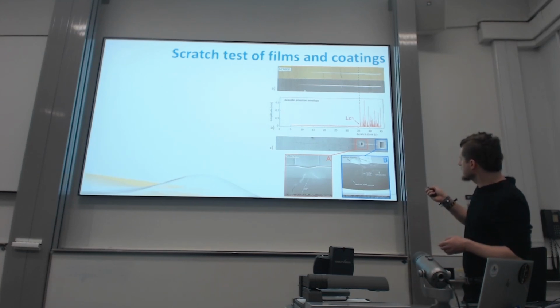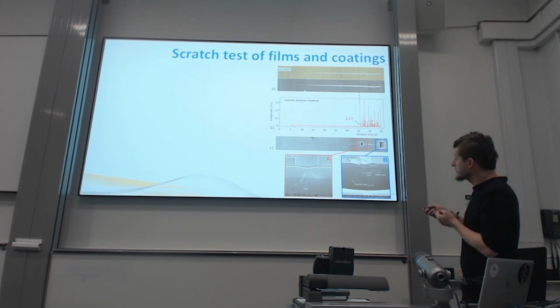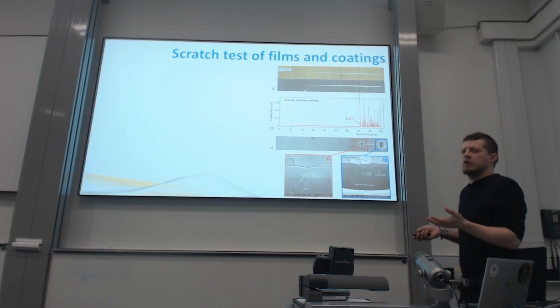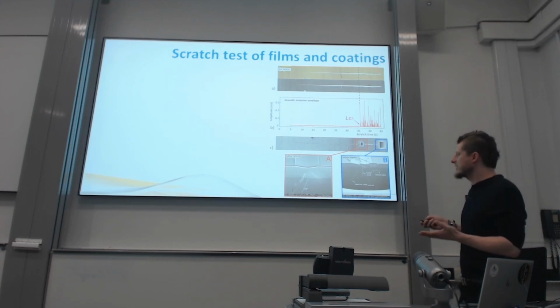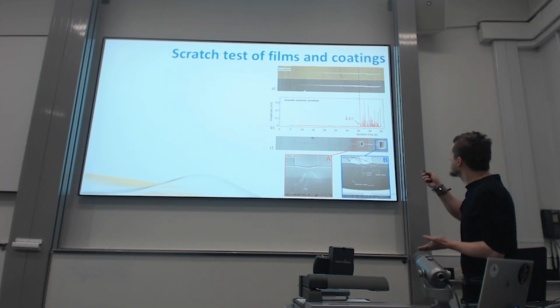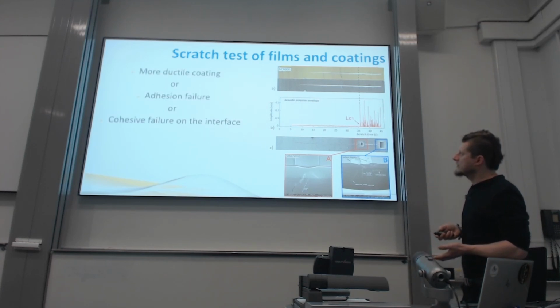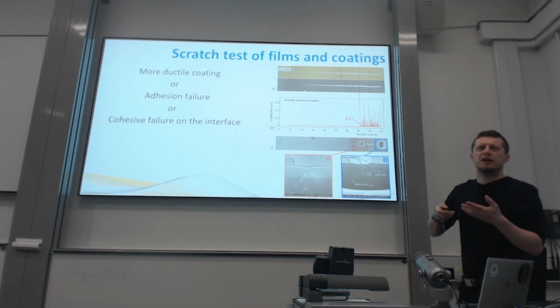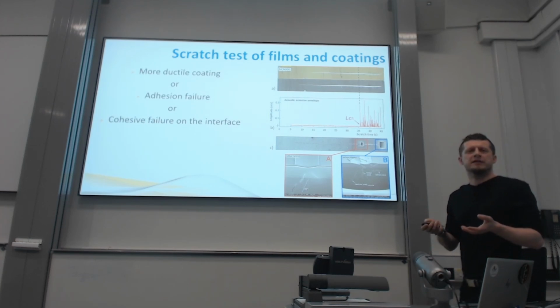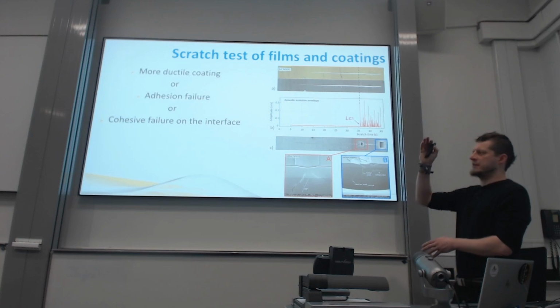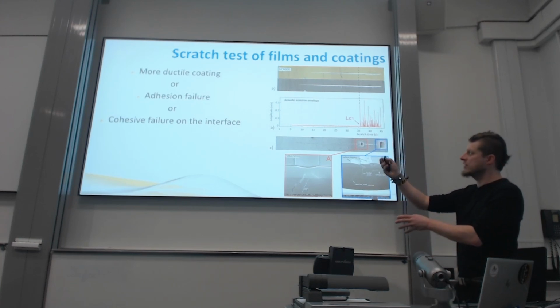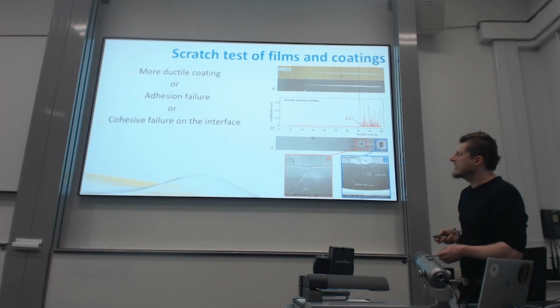At the latest part, there's a big crack going up to the surface, but from the cross-section it looks so nice. In this moment, it helped a little, because you want to detect the first critical load. This is it, not this. So it can be helpful in more ductile coatings. Let's say a brittle coating would break instantly. You would have it in a microscopic image and in depth change, but a more ductile one can be detectable preferably by acoustic emission.